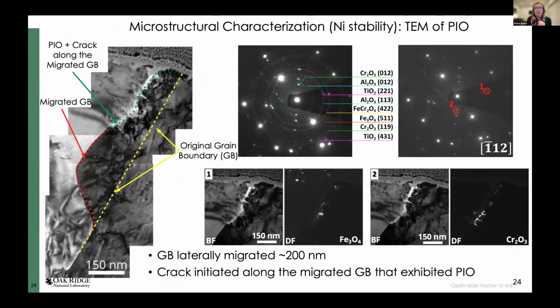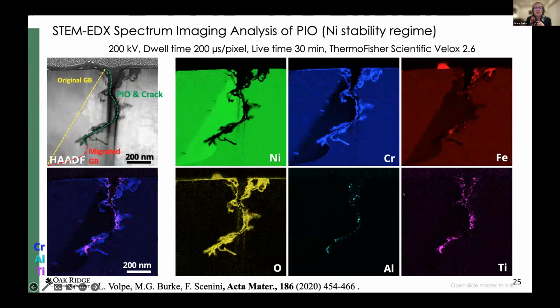So let's look at that under stress. We can do that. We see our migrated grain boundary, we have our crack, and because we're doing TEM characterization of this, we can do selected area electron diffraction and index the various oxides that are present, and we can image the various ones. So we've got the spinel, the Fe3O4, and we can also index the chromium oxide.